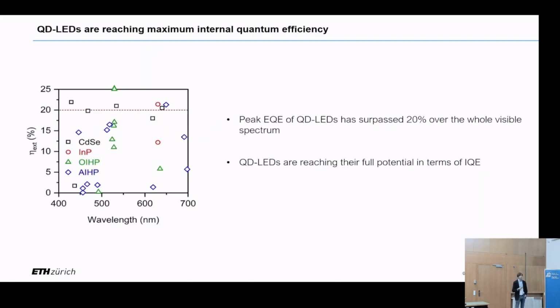But what about quantum dot devices? Here I reported a probably non-exhaustive list of recent very high efficiency devices that have been reported in the literature among the three most promising material platforms, which are cadmium selenide, indium phosphide, and lead halide perovskite. And as you can see, a lot of devices are now breaking the 20%, even 25% barrier, more or less across the whole spectrum, apart from deep blue. And that means that these materials and devices are reaching their maximum potential in terms of internal quantum efficiency.